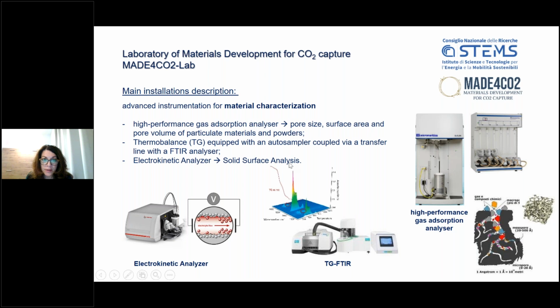A thermobalance equipped with an autosampler coupled with a transfer line with an analyzer of infrared type. This is very important to obtain a clear idea of the thermal performance of the material and also of the evolution of the material after a thermal treatment or under dynamic condition. And lastly, an electrokinetic analyzer that will be very useful to obtain a solid surface analysis in terms of surface charge.